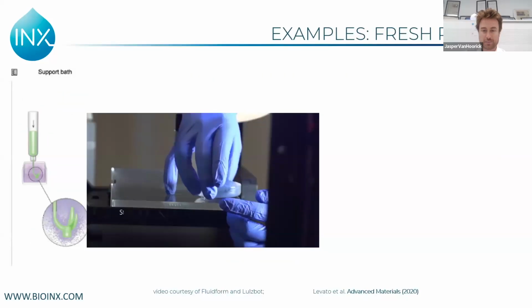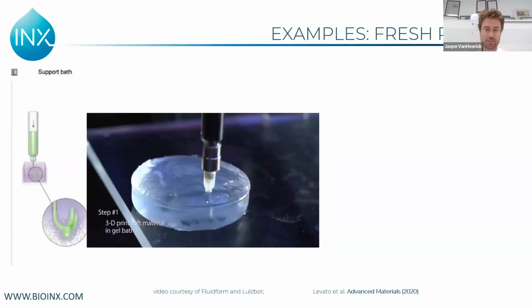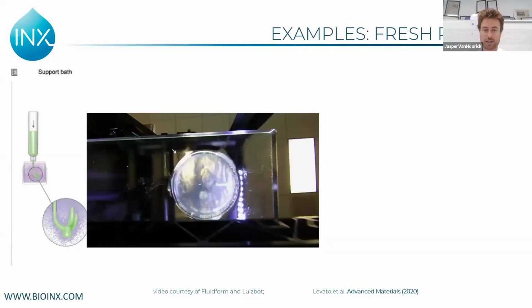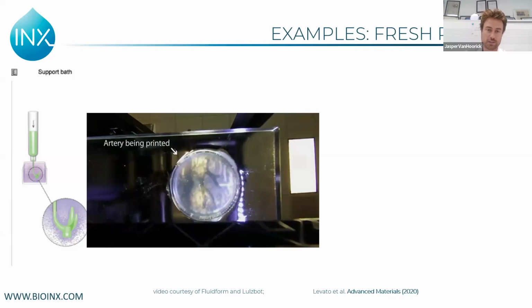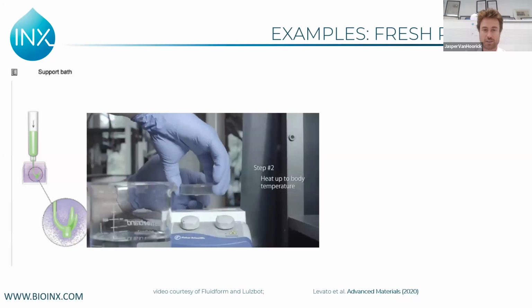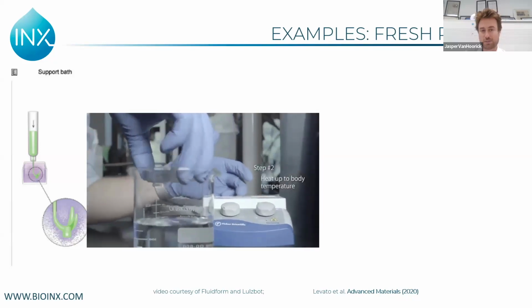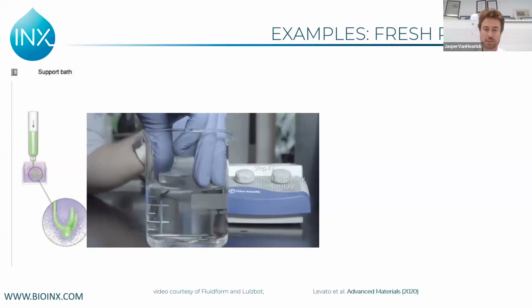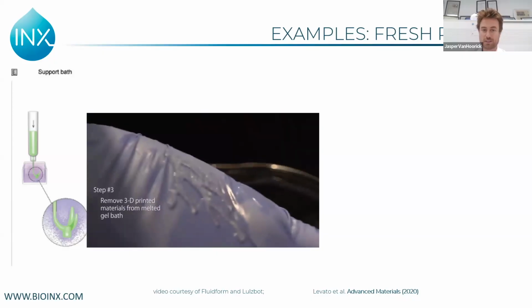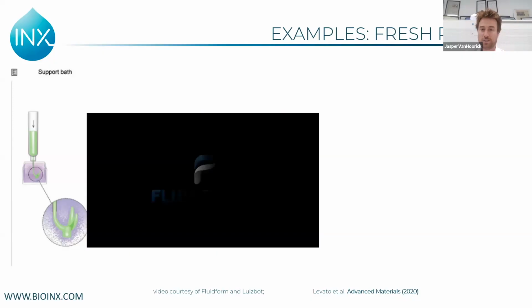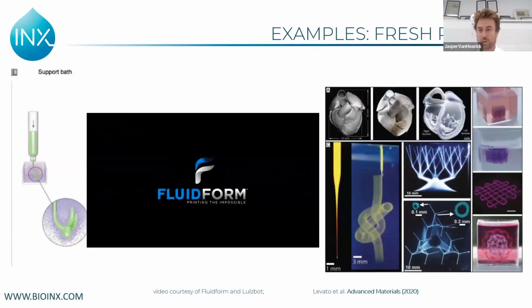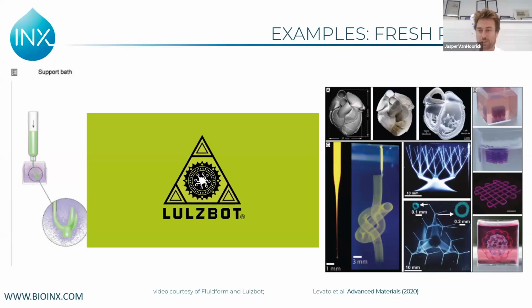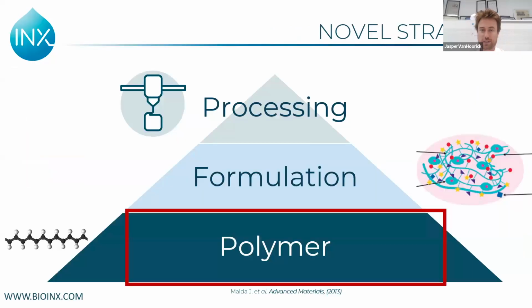And another strategy is, for example, the use of a support bath. So here you use a granular support bath of hydrogel beads in which you print your structure, and then the support bath supports your material. If you afterwards put it in water or warm water, the support bath dissolves and you can get your complicated 3D printed structure. And with that, even with extrusion, you can already get quite some interesting structures with materials which are basically unprintable if you would do it in a conventional way.